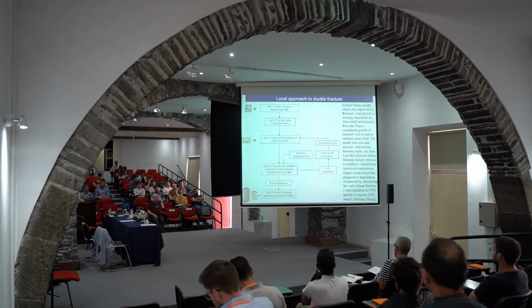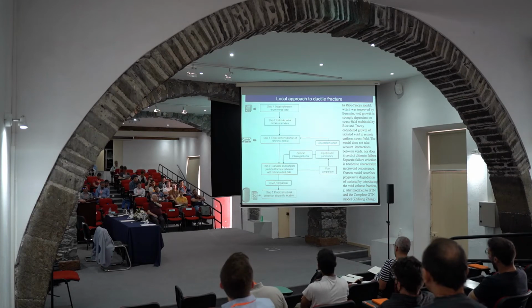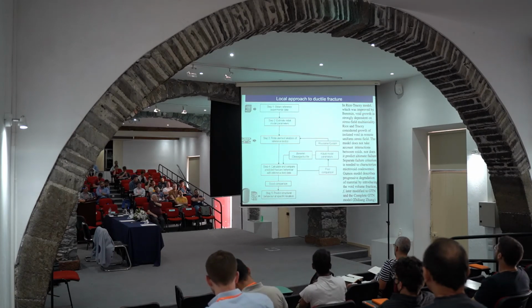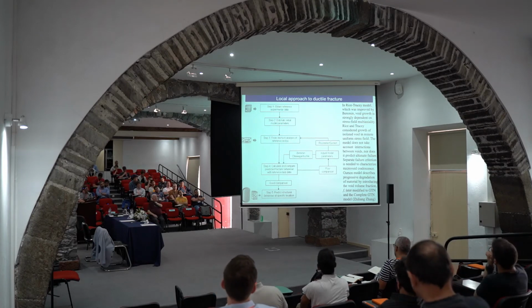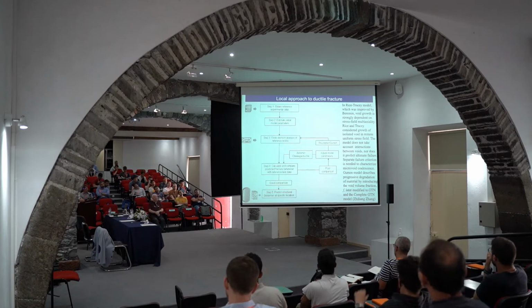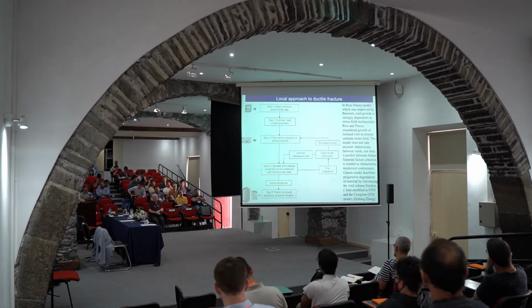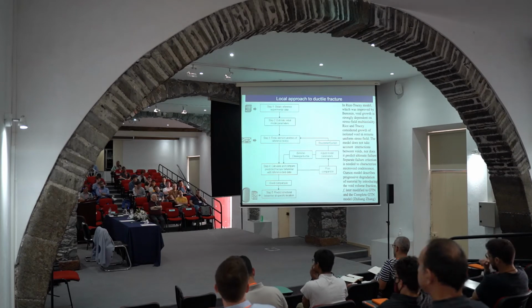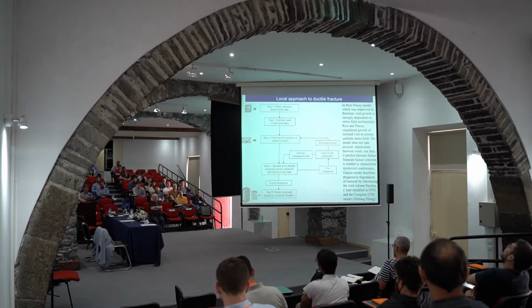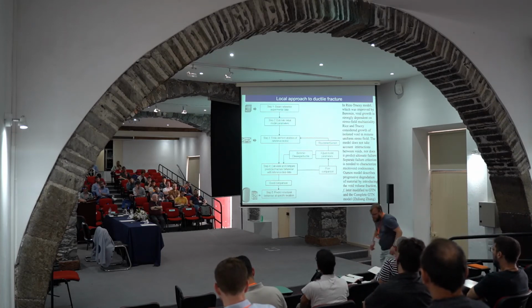So what we are doing here is how to use results obtained on specimens on a real structure. So it's not completely new, because I already mentioned that problem, which is of course always present in our practical life. This whole approach, which is either called local approach or micromechanical modeling, was initiated by this need to know what is the difference between behavior of a crack in a specimen and a crack in a real structure. I just mentioned that a crack in a 3-point bending specimen would behave differently than a crack in a pressure vessel or in a tensile panel, and these differences are not small. So this micromechanical modeling is one way to reduce unnecessary conservatism in our approach.